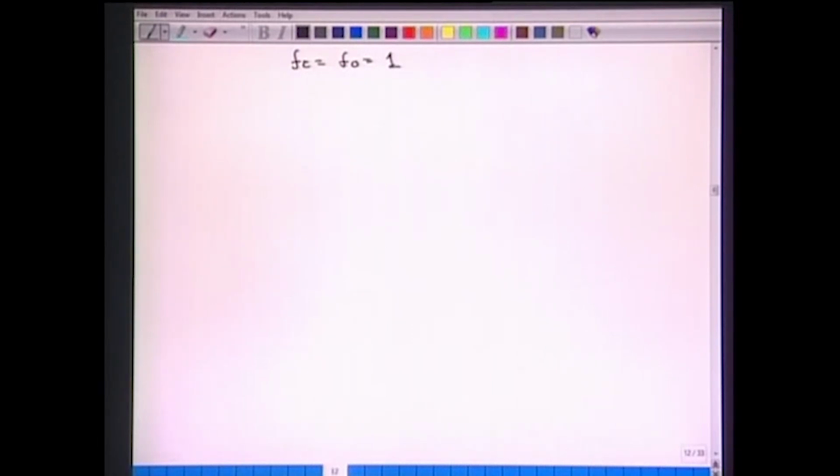If I substitute that into equation number 22, then I get weight percent carbon into weight percent oxygen equal to PCO upon KCO. Now, this equation suggests that the product of weight percent carbon and weight percent oxygen depends upon the partial pressure of carbon monoxide and the value of KCO.